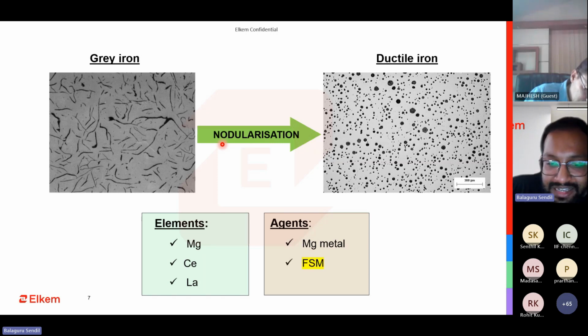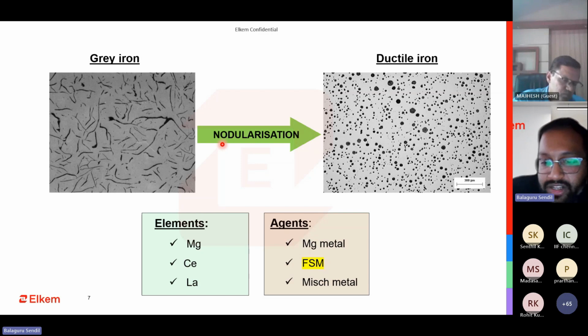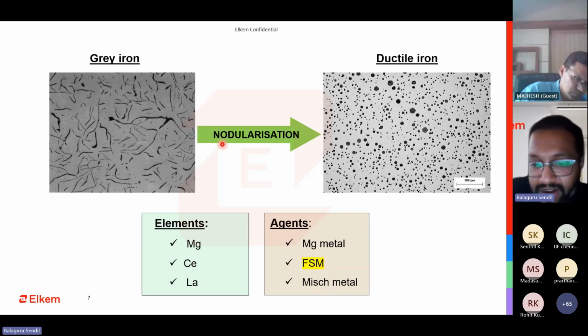The other one is ferrosilicon magnesium, where you have magnesium combined with iron and silicon. Both of these act as carrying elements and make sure that the magnesium comes into the liquid metal during treatment at a controlled level. And the last one is Misch metal, which is also used. Misch metal is a combination of rare earths. The rare earths most commonly present are cerium and lanthanum. This can also be used as a nodularizing agent. So these are the various elements that cause the effect of nodularization.